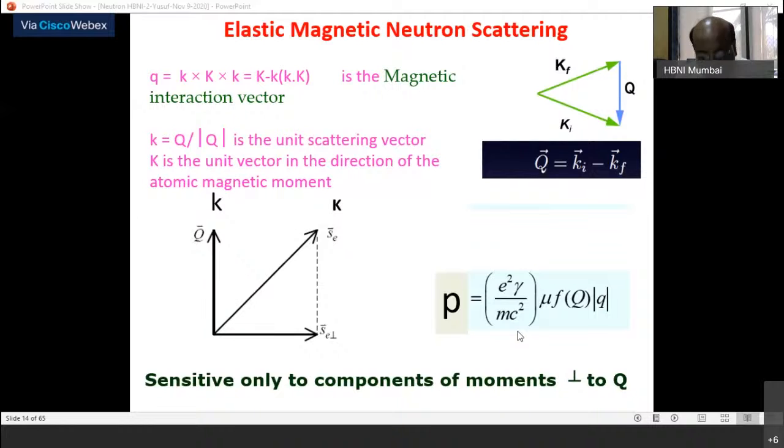See, X-ray being electromagnetic radiation, there is another field vector which is called the magnetic field vector. So E and B, right? E and H. But what happens is in any electromagnetic radiation, as you know, amplitude-wise the electric field vector is about 2 orders of magnitude stronger. So the magnetic field vector in any electromagnetic radiation is about 2 orders of magnitude weaker than the electric field vector. So when you do the scattering experiment, cross-section-wise it is 4 orders of magnitude weaker, because amplitude-wise it is 2 orders.